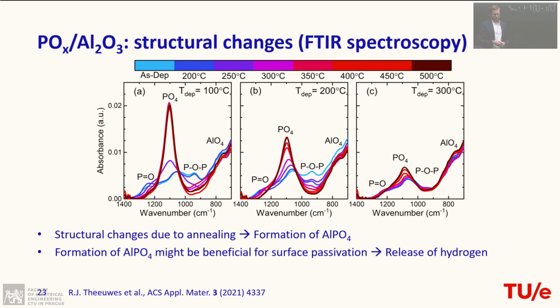If we then investigate in a bit more detail what the structural changes look like, we use FTIR spectroscopy, also a very popular technique to look at thin films. In this way, we see that certain bonds are much more pronounced after you anneal, while others disappear. What's especially interesting is that you form aluminum phosphate, this AlPO4, and it might be beneficial for surface passivation, while you also release hydrogen towards your silicon interface.